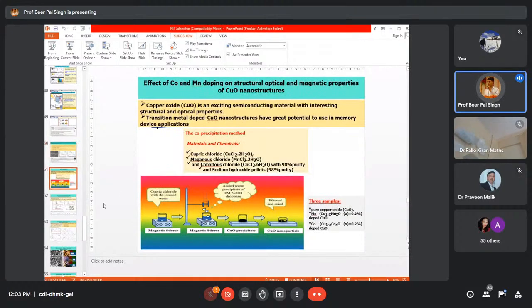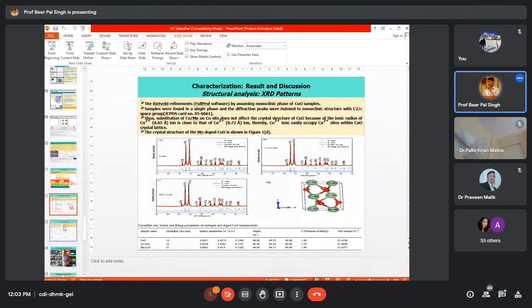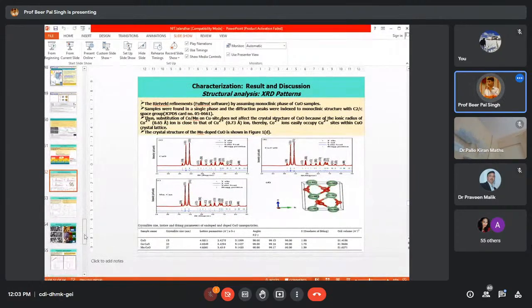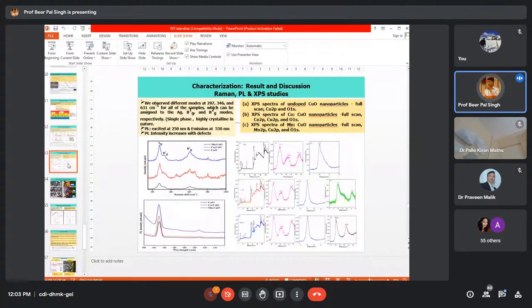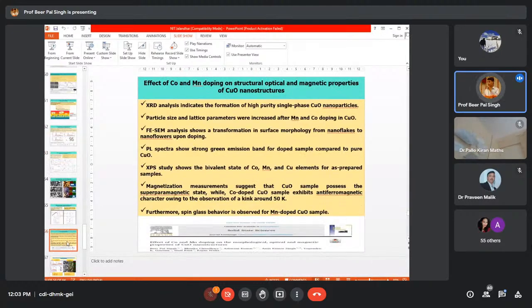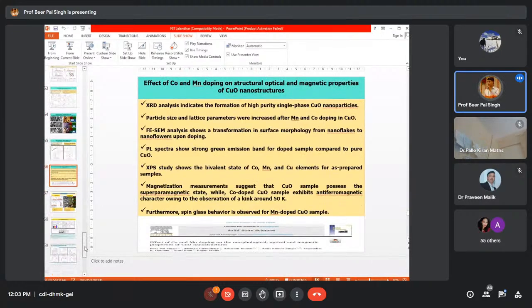This is about copper oxide. One of my students studied copper oxide well. She synthesized copper oxide nanoparticles, did doping of Co and Mn, and ultimately changed the magnetic behavior of copper oxide by doping. These are the results of XPS, Raman and PL of this material, and ultimately she published it in Solid State Sciences, published by Elsevier again.